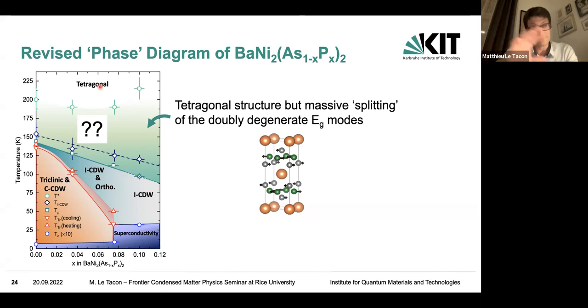Thank you. But that's the point where I went to see Jörg Schmalian, and I said, well, look, I have this. It's quite clear. On the one hand we have Christoph, who is the official authority in Karlsruhe to tell us when there is a phase transition or when there is no phase transition. And it's fairly clear there's no phase transition at this temperature in this compound, and yet we do have this splitting. Our X-ray specialist Michel tells us that at that temperature the system is fairly tetragonal, and we see no sign of splitting of the line. So we do have a tetragonal system, but we do have a massive splitting of the EG mode. What's going on? So Jörg is very smart, and then he looked at me and said, well, there's no splitting. Well, it took him a week to say that, but that's the way of saying it.